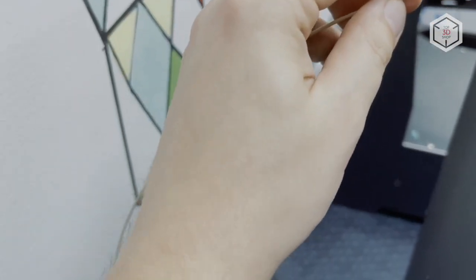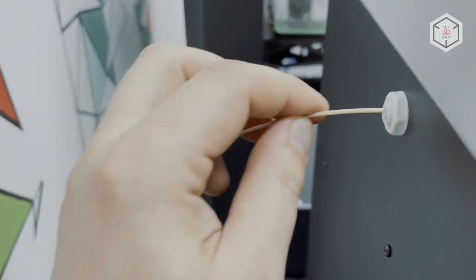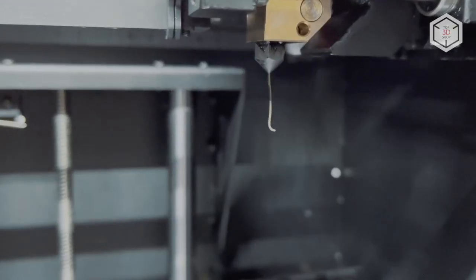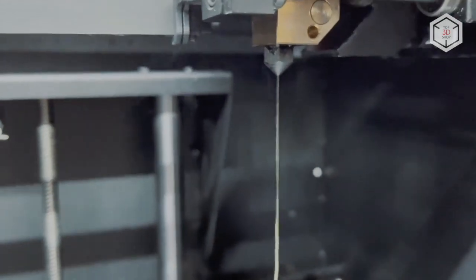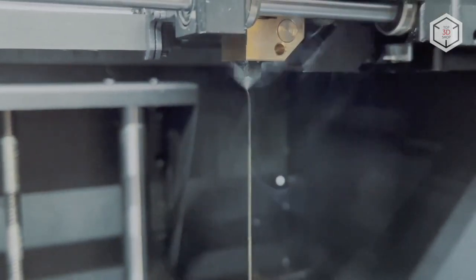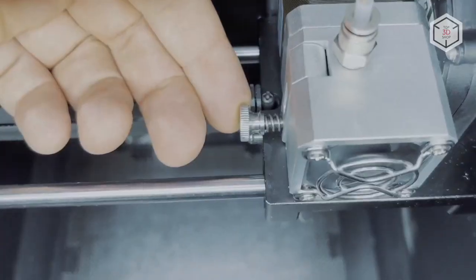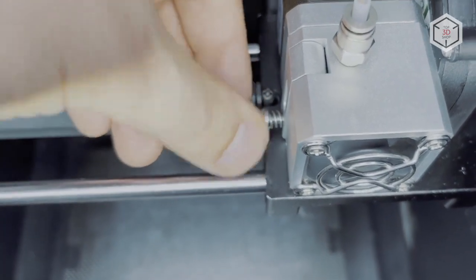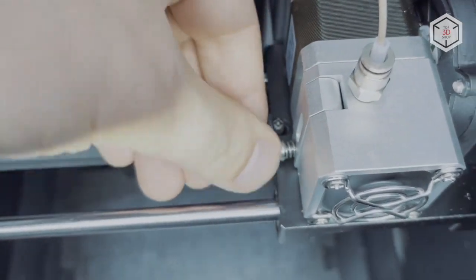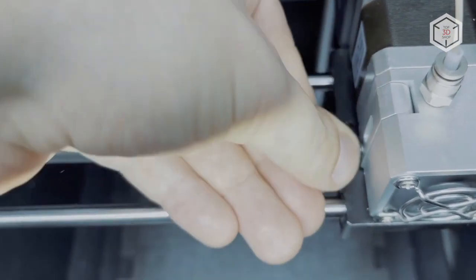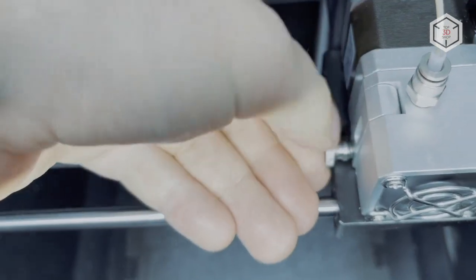The filament feeding mechanism is as follows. We decided not to install the standard holder for test printing. We just slightly loosen the side spring holding the filament and mechanically push the thread until it comes out of the nozzle, melted. When the process is complete, we tighten the spring as much as possible. PEEK is a solid filament, so there's no need to worry about overpressing it. And to keep it from slipping in the gears, it has to be pressed properly.